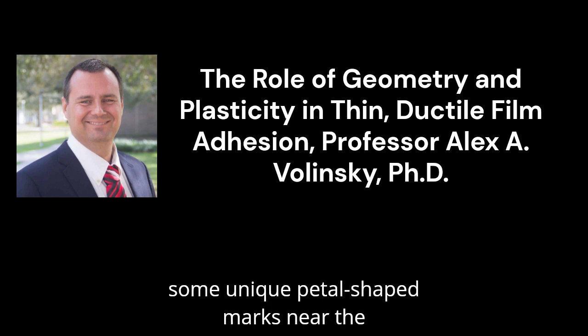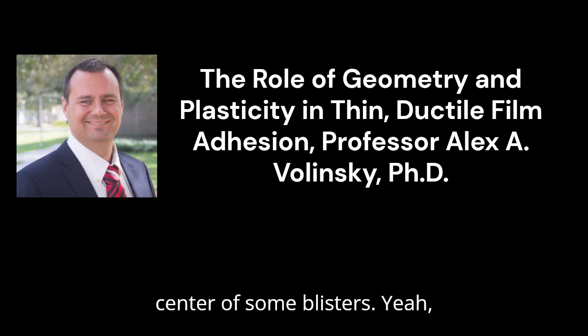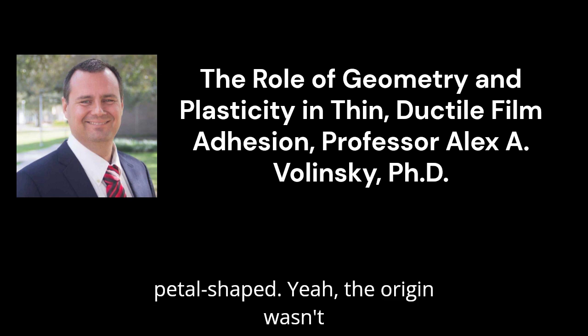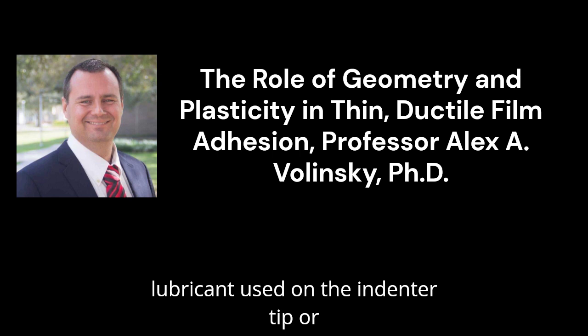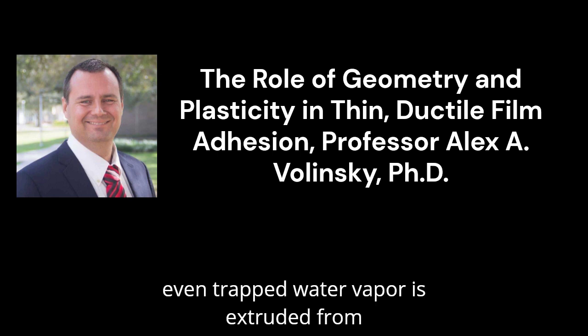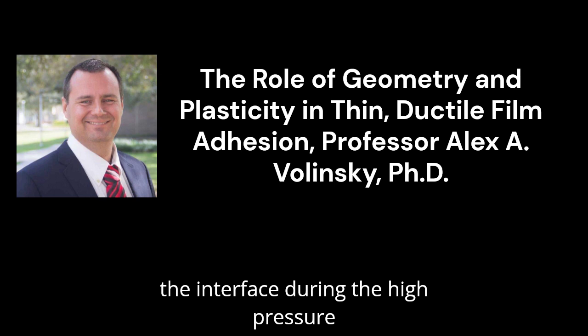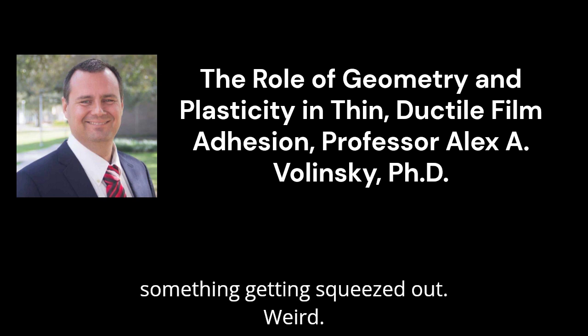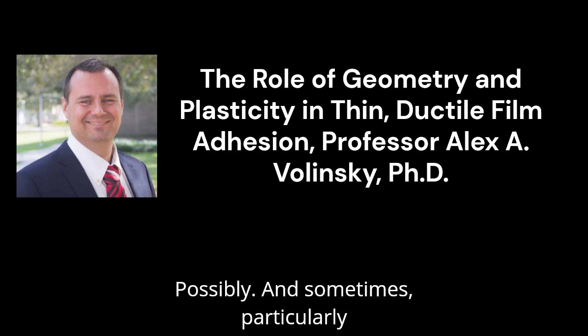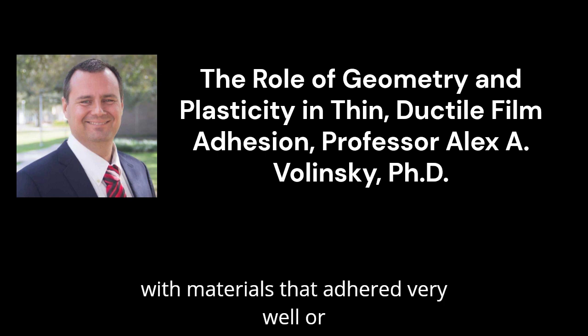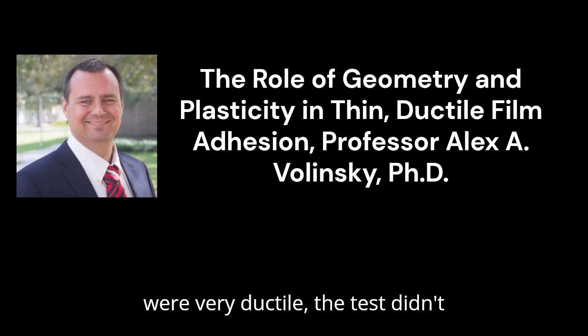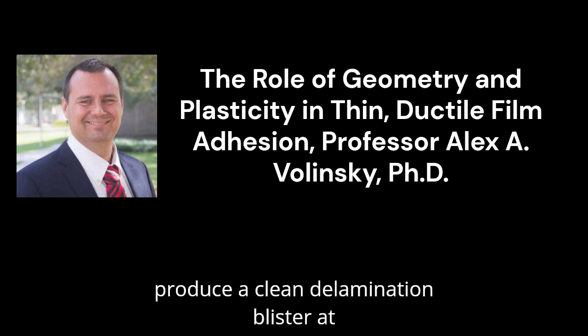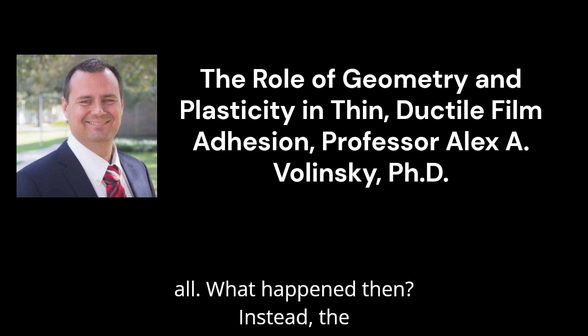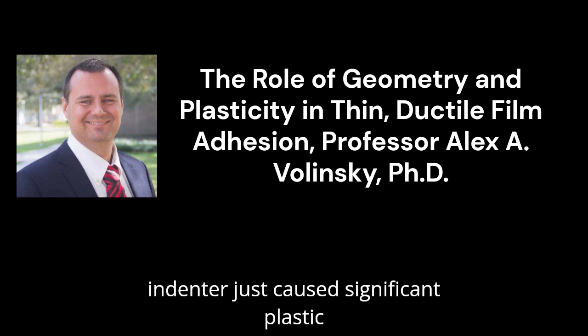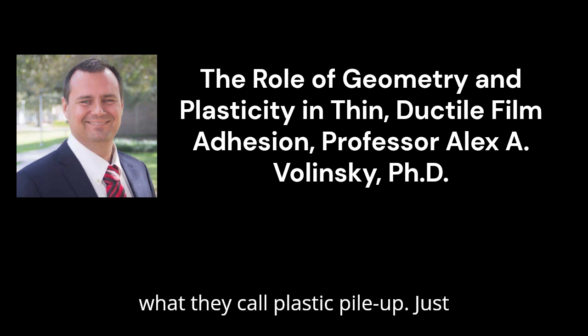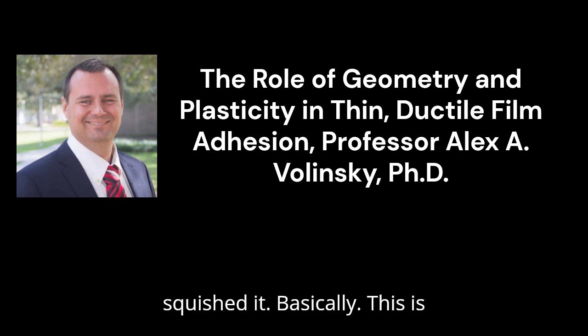They also found some unique petal-shaped marks near the center of some blisters. Petal-shaped. Yeah, the origin wasn't fully clear, but might relate to how lubricant used on the indenter tip or even trapped water vapor is extruded from the interface during the high-pressure indentation. Like imprints left by something getting squeezed out. Possibly. And sometimes, particularly with materials that adhered very well or were very ductile, the test didn't produce a clean delamination blister at all. What happened then? Instead, the indenter just caused significant plastic deformation in the film and superlayer, what they call plastic pileup. Just squished it. Basically.